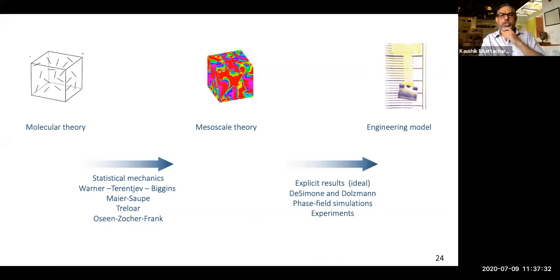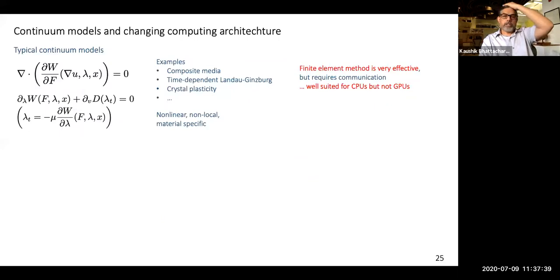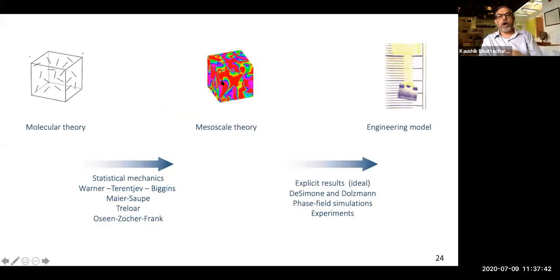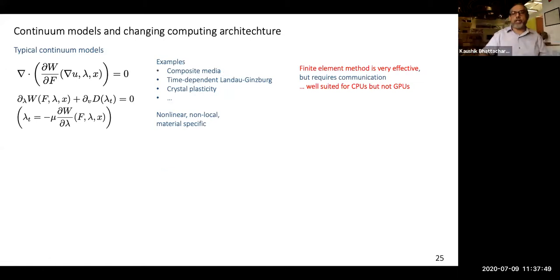So I'd like to take a minute to talk a little bit about numerical methods, because the simulations I showed you can be quite expensive. You have an internal variable, you have elasticity going on. And this is something that you find in a lot of very different continuum solid models. So the typical model looks like this. You have the deformation, you have an internal variable, you have some kind of equilibrium or dynamic equation, and then you have an evolution equation for your internal variable. So in our case, the internal variable was the director. Now the difficulty is, of course, this is spatially second order, nonlinear. This is first order in time.